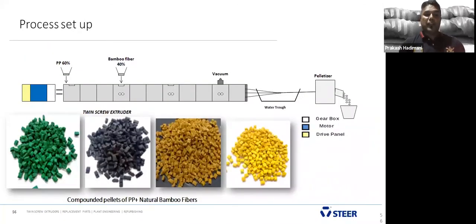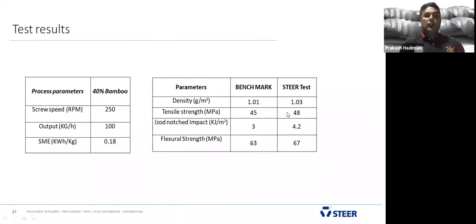And there are many colors we have added in the bamboo compounds, green, and many other colors can be done using bamboo powder. This is the same setup, using polypropylene and bamboo powder. Bamboo powder was 40% from the side feeder. When it comes to testing and results, we could manage 100 kg per hour in the 40 millimeter. See the density, the benchmark we got 1.01 and 1.03.